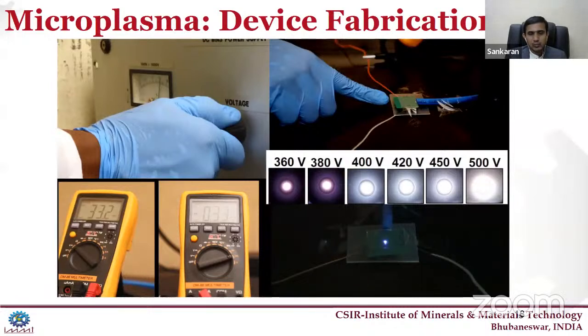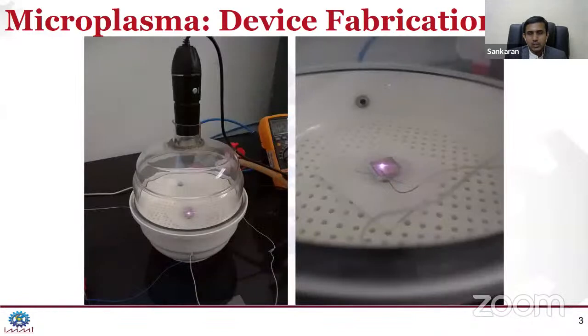This is the study that we are doing now at IMMT to develop a robust and high lifetime stability cathode material to be applied for the microplasma devices. With these parameters, we are going to characterize this material. This is another device we have fabricated inside a small chamber, a desiccator. We have also created a vacuum in this chamber, and we pass only the argon gas so we can generate the plasma here.